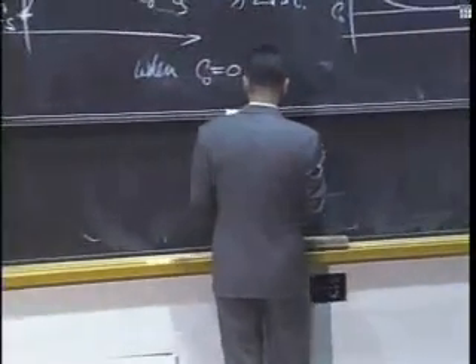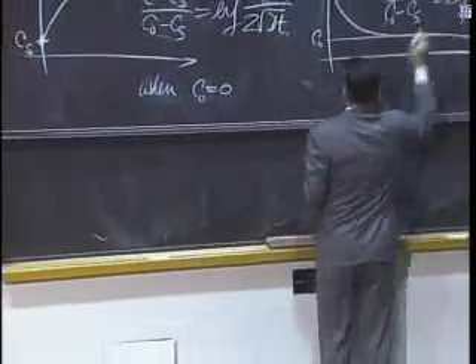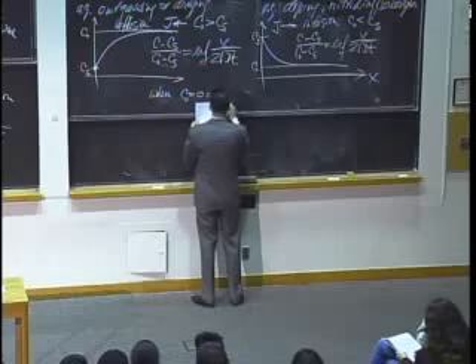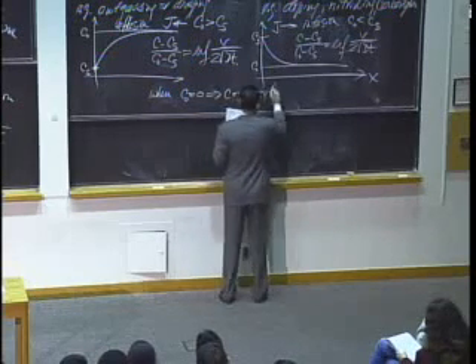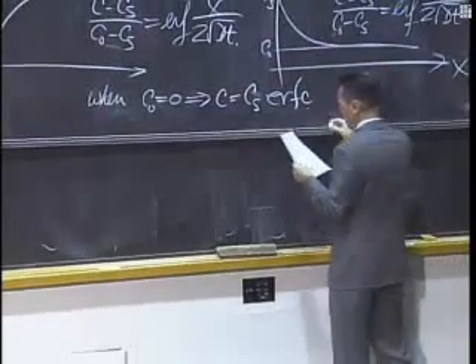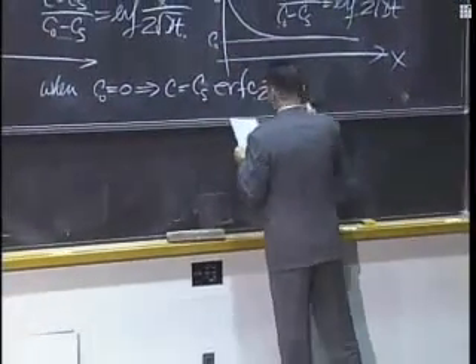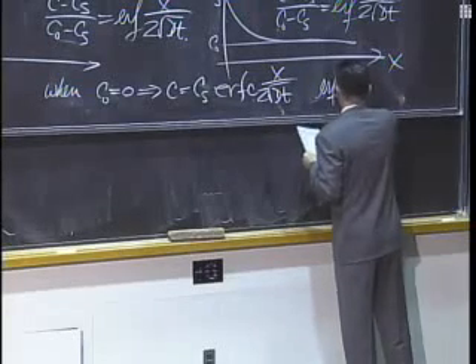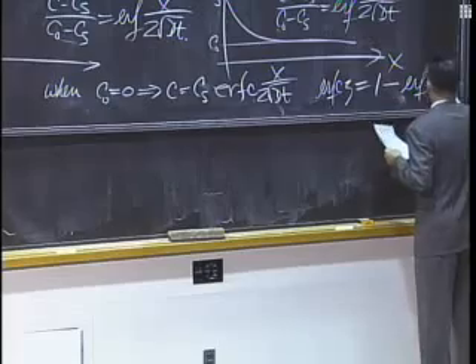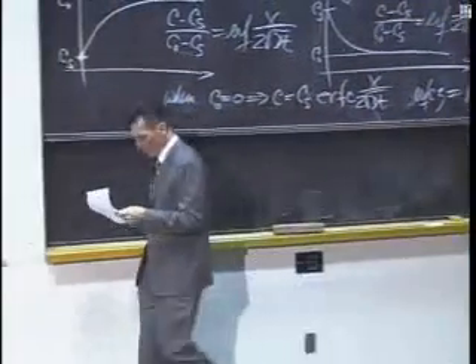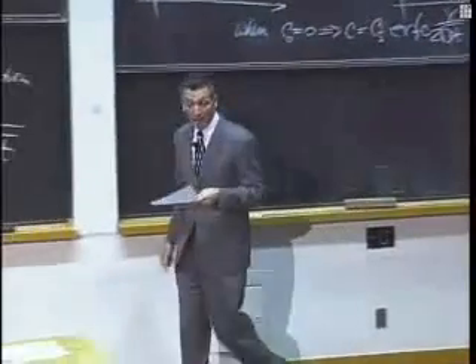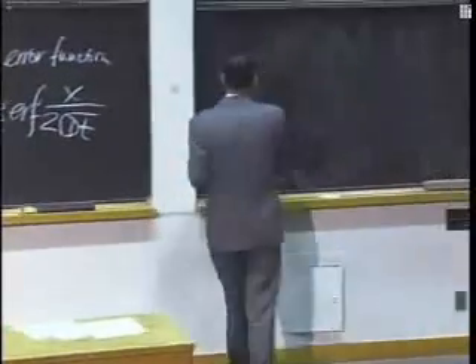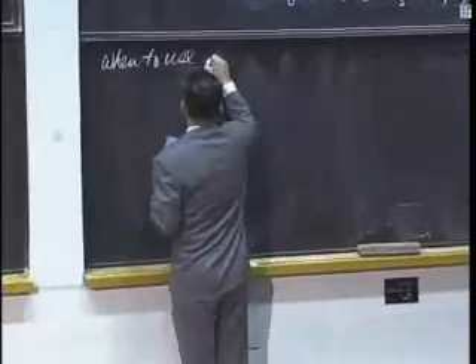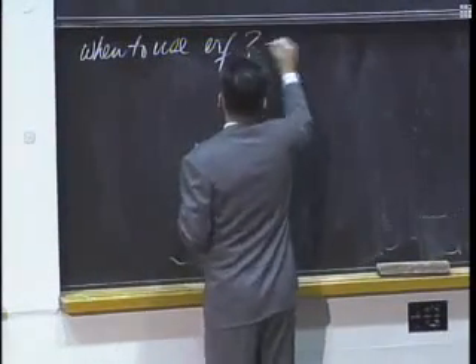So for many of those cases, if you go through the math, this is a 0. Transpose, and you'll end up with this as the solution. C equals Cs times the complementary error function, ERF complement, of x over 2 root Dt, where the complementary error function, ERF complement of z, is simply 1 minus ERF of z. So if you see that in the literature, that's all they're doing. So now the question is, I've told you that there are special conditions that validate the error function solutions. What are the conditions? When to use ERF? Because that's not the only solution to Fick's second law.